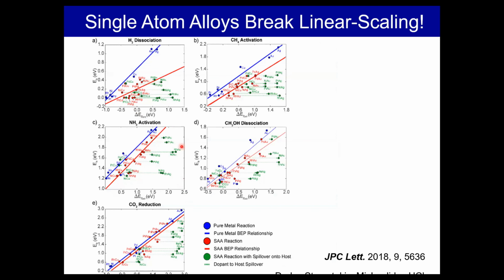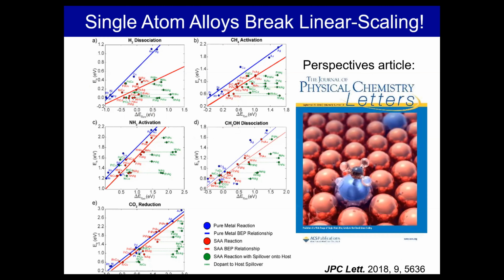And then relevant to this meeting, a lot of these combinations will give you different scaling relationships or completely break the scaling relationship. So again, this is calculated activation energy on the y-axis, reaction energy on the x-axis for hydrogen dissociation, CH activation, NH activation, and so on. The blue lines are the linear scaling for the pure metals. The red points are for the single atom alloys. So you see in a lot of cases, you're actually lying underneath the blue line, which is good because you have lower activation energies for weak binding of intermediates. I'd encourage you to take a look at this perspective article in JPC Letters, which I borrowed the title for this presentation, for a discussion of all these different properties predicted from theory.